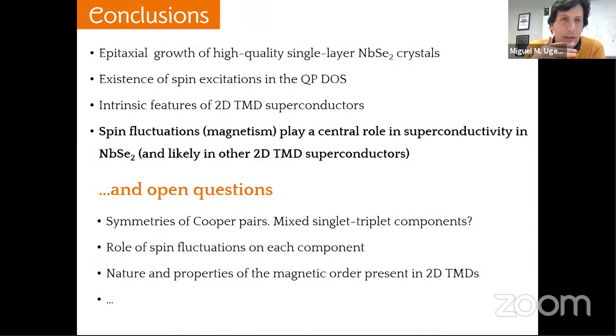Okay, so with this, let me just wrap up my talk. We have been able to grow high quality crystals of single layers of niobium diselenide. We have demonstrated the existence of bosonic modes, which we believe are spin excitations in the quasi-particle density of states. These are clearly intrinsic features of niobium diselenide and intrinsically related to superconductivity.